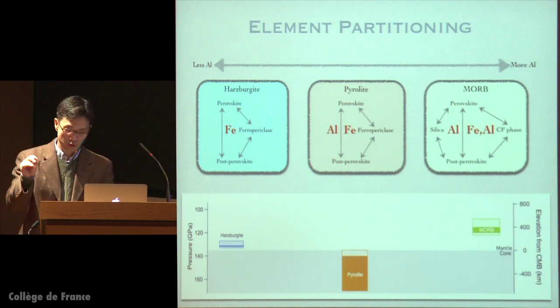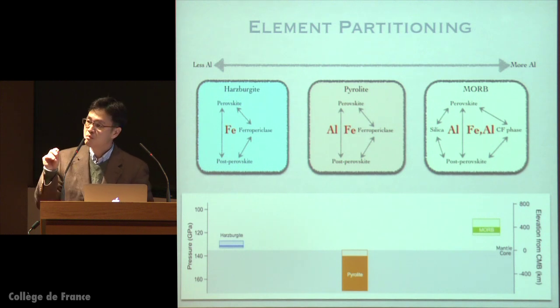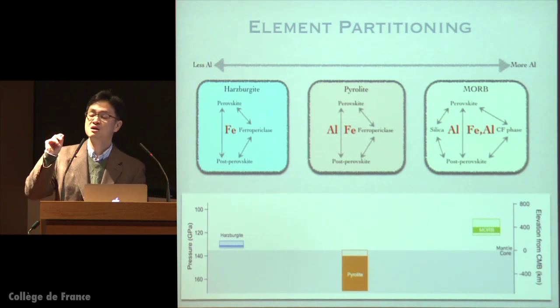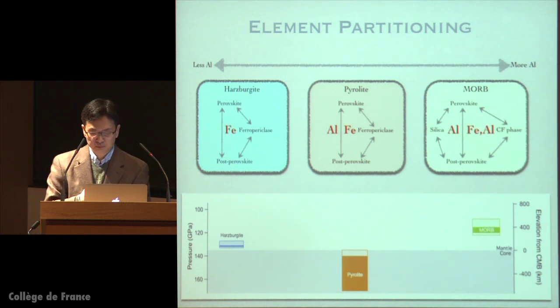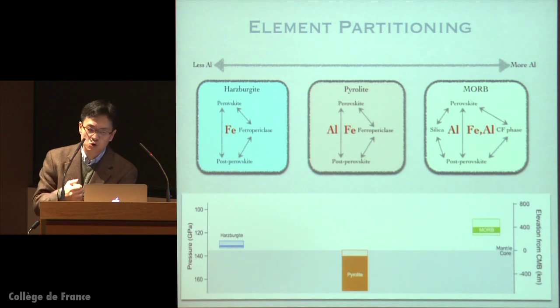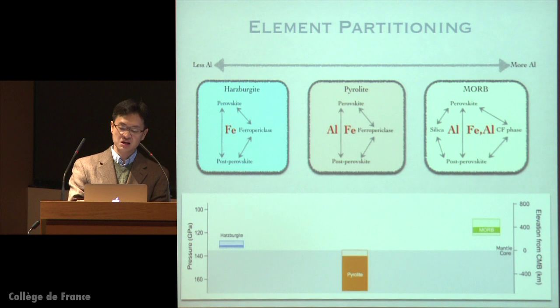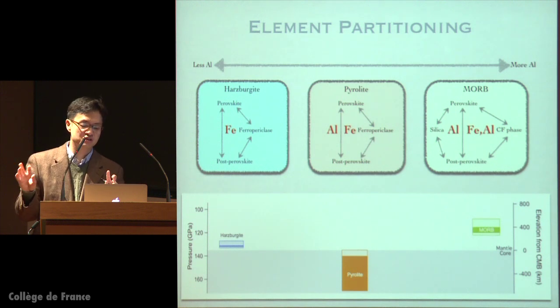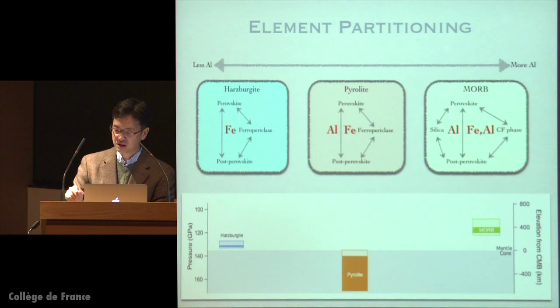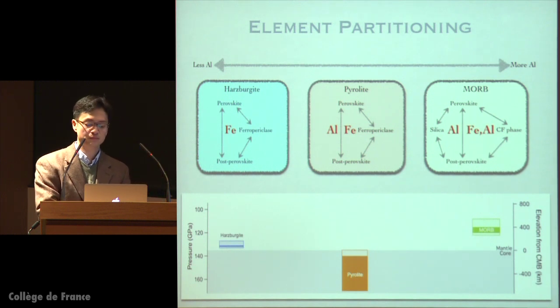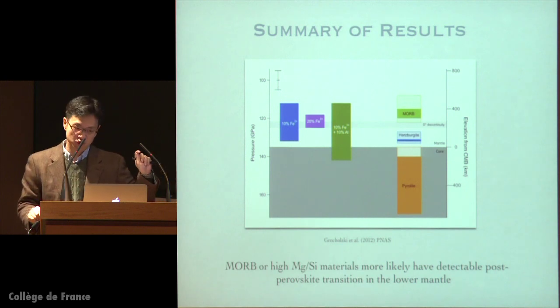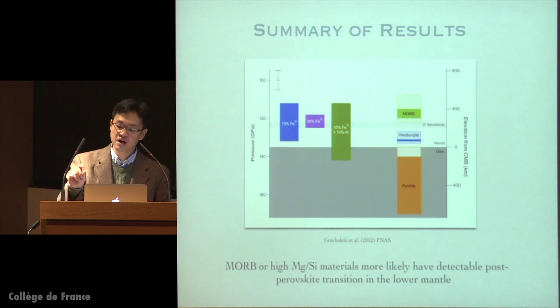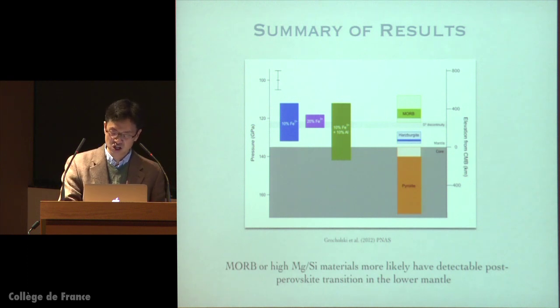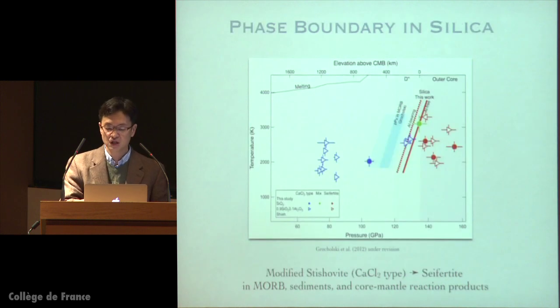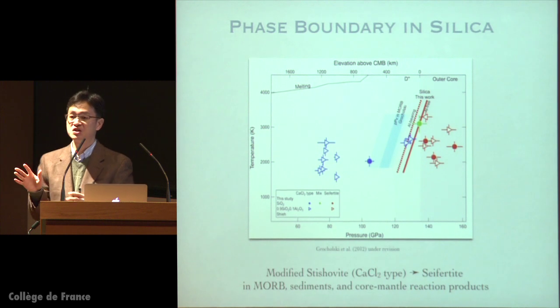Pyrolite has ferropericlase, so it perhaps controls iron, but it doesn't have a phase that can control aluminum, and that leads to the larger thickness and the deeper depth. And finally, for morb, even if we have more aluminum than any other system, because it contains secondary phases that are capable of containing aluminum and iron, we believe that those minerals, well, they are no longer secondary minerals, I shouldn't say that, have a controlling effect on the thickening from aluminum and iron. So this slide summarizes what we have seen so far. It seems that the mineralogical effect is quite big for understanding the thickness of the post-perovskite discontinuity among different systems. So now I'm going to talk a little bit about other systems. This is the 21st slide.